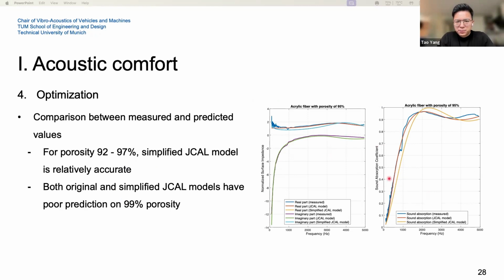I didn't put the graph here, but we got a problem for the highly porous material, which is 99% porosity. Both the original and simplified JCAL models can't predict the sound absorption and the surface impedance in good agreement. So I'm still trying to figure out the reason for this. I guess it might be because of elastic movement, because it's quite highly porous, the fibers may start to move. So that's why it happened, but we need to do further investigation.